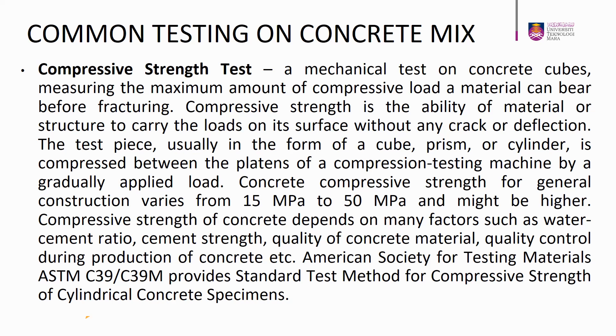Another common test for concrete mix is the compressive strength test. This is a mechanical test on concrete cubes, measuring the maximum amount of compressive load a material can bear before fracturing. Compressive strength is the ability of a material or structure to carry loads on its surface without any crack or deflection. The test piece, usually in the form of a cube, prism, or cylinder, is compressed between the platens of a compression testing machine by a gradually applied load. Concrete compressive strength for general construction varies from 15 MPa to 50 MPa and might be higher. Factors affecting compressive strength include water-cement ratio, cement strength, quality of concrete material, and quality control during production. ASTM C39/C39M provides the standard test method for compressive strength of cylindrical concrete specimens.